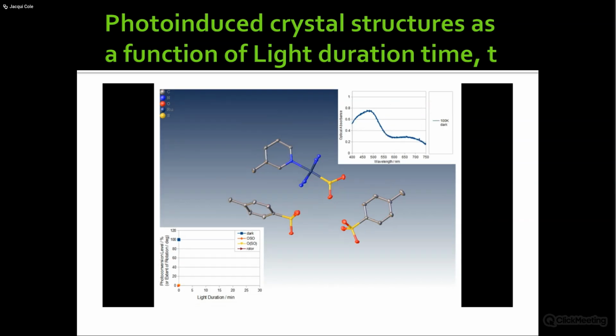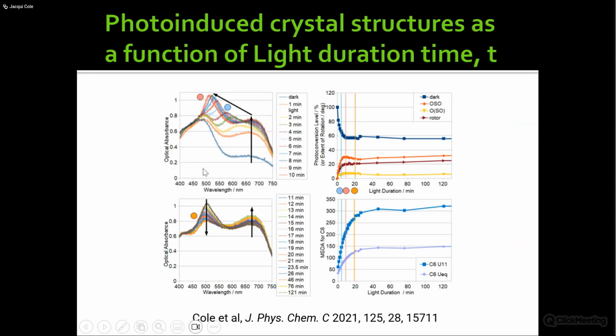We sought to see if we could actually put a mechanism on that. And we tried to then classify it into sort of steps, if you like. So this part, there's clearly from optical absorption spectroscopy a rise in absorption at, let's say, 660 nanometers. And then you've got this rise in this kind of almost saturated peak formation.